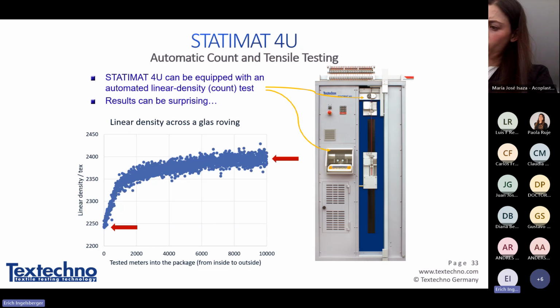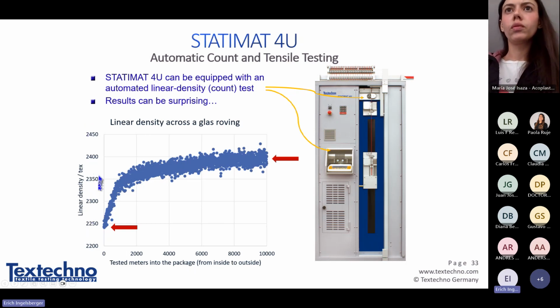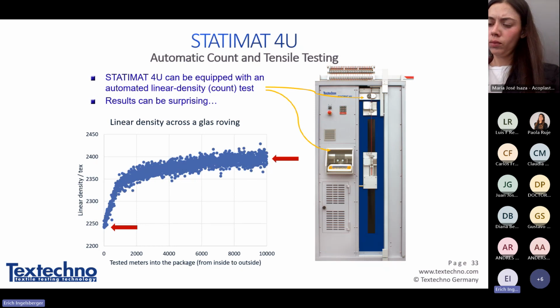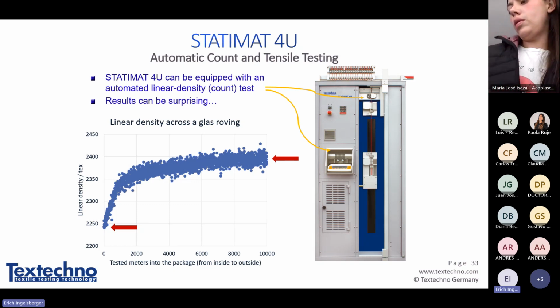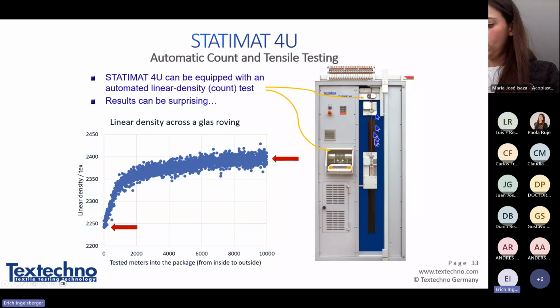We tested a glass roving, and this shows the weight in gram per 1 kilometer length, which at the start had a certain value, and then going deeper into the package, the linear density, meaning the weight or even the diameter of the fibers, increased, something we did not expect. We started using this instrument only to test tensile properties, but then found this interesting effect. Just very briefly about the tensile tester.